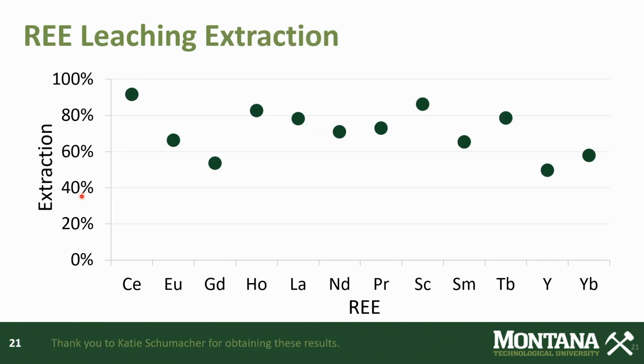Okay, this slide indicates some representative leach extraction efficiencies, and these would be obtained from the actual concentrate after it had been chlorination roasted and leached. So this is a key, and you'll see it's almost a little bit of a scatter shot, and I'll explain that briefly. But the thing to take away from all of this, you see the lowest point on this might be around 50%. Well, about 50% is the best they do in current hydrometallurgical operations. So this indicates that if everything else downstream of the roasting and leaching fails, we've at least come up with a way to recover more rare earth elements.